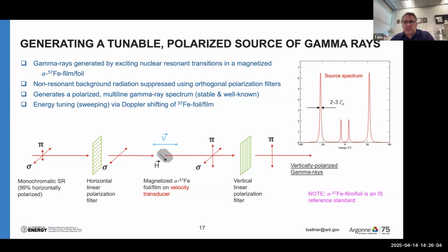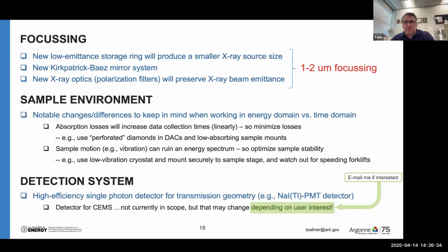This approach has some real advantages in terms of stability because it's a forward scattering approach. It doesn't impact the focusing capability, so that's why we're going with this approach. Also the emitter is alpha iron, which is a standard isomer shift reference material. That's just a benefit. The focusing takes advantage of the low emittance storage ring, of course. The new KB mirror allows us to get down to 1 to 2 microns, and the polarization optics will be designed so that they preserve the X-ray beam emittance, and so there's no source broadening that might occur otherwise. It's the kind of broadening that happens in the iron mono and the vibrational spectroscopy, and that will not be there. So we'll be able to focus down to 1 micron.